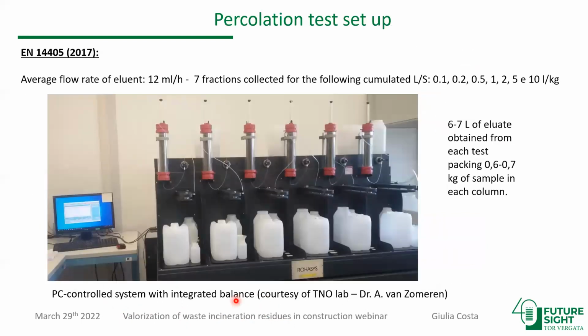So this is a picture of the percolation test setup that we have been using that has actually been donated to us from TNO, and we thank Dr. Van Zomeren directly. And in this, here we are able to carry out 6 tests in parallel, and in each test we use around 700 grams of sample and obtain 7 liters of leachate in the end, and around half we analyze and half we send for the ecotoxicity tests.